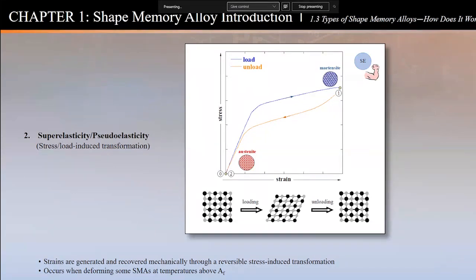stress-induced transformation. How does this happen? Now I'm sitting at 0 here. My microstructure is austenitic, cubic. I start loading this material. At some point, it starts transforming to martensite, and then finishes the martensite. And then as I reverse the load, it comes back through this path, austenite, and then it finishes the austenite. This is just pull it and let it go, basically. Load and unload. This is fully reversible, what's known as superelasticity. The principle is the same. It's a phase change. It goes from this nice cube to the shear components, and once you unload, it goes back to this cube. So the underlying principle is exactly the same, except that this is triggered by load versus the shape memory effect, or SME, which is triggered by temperature.